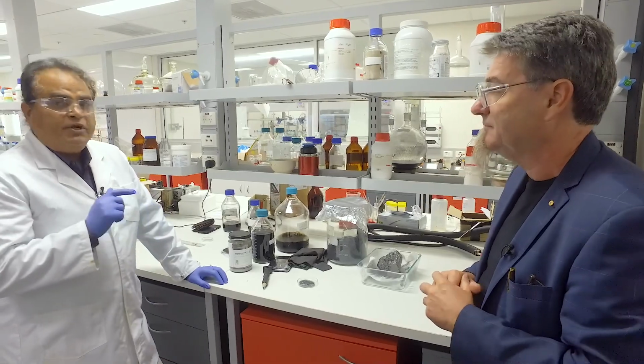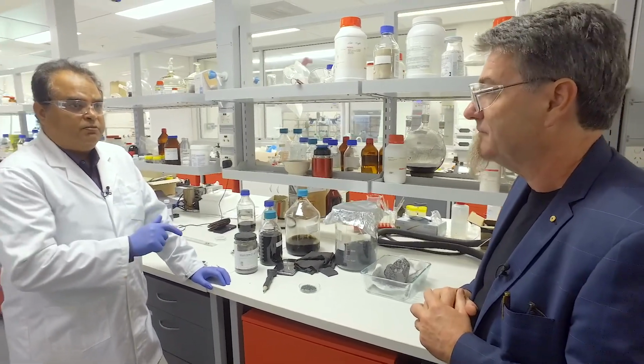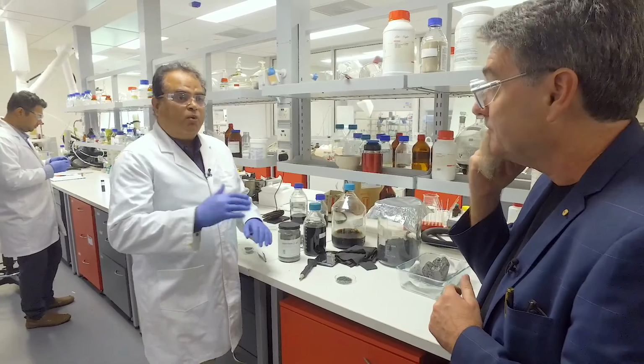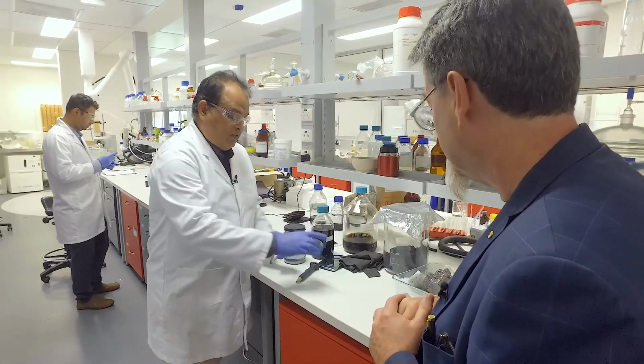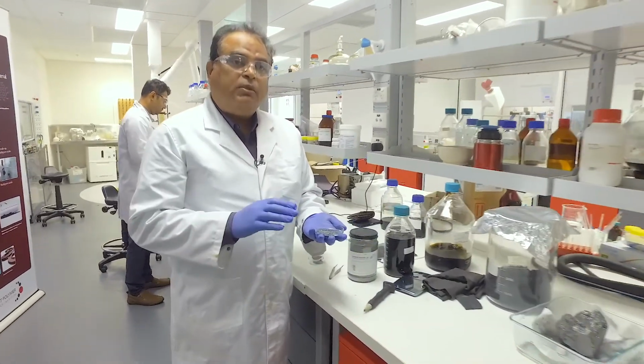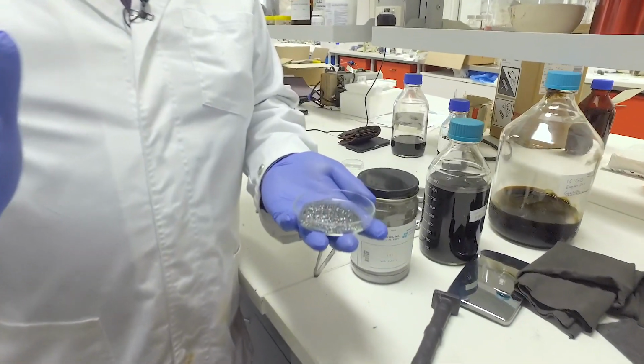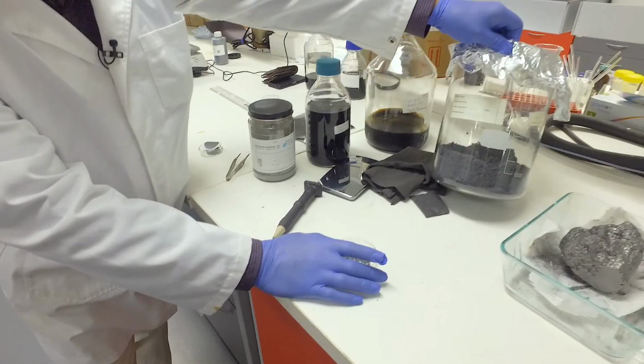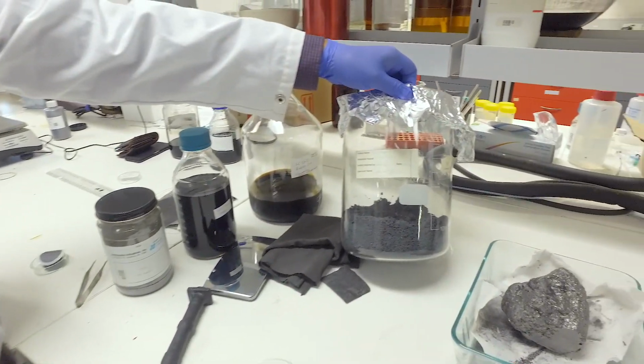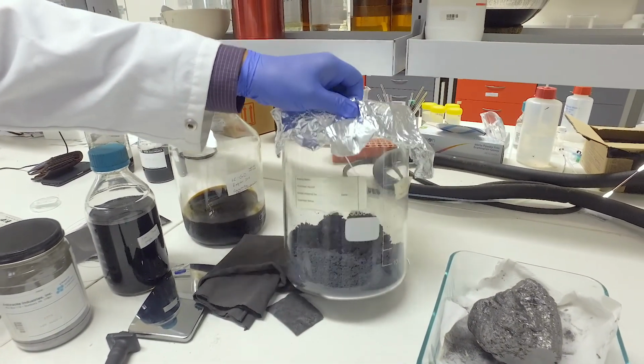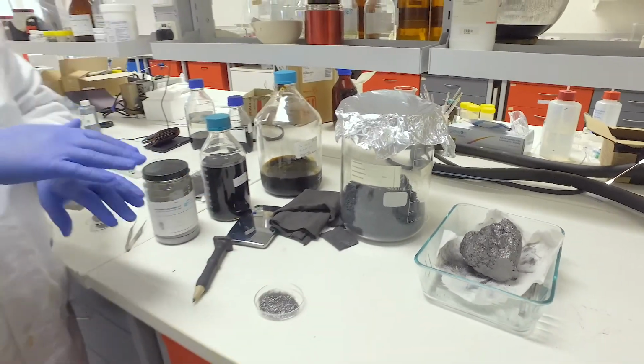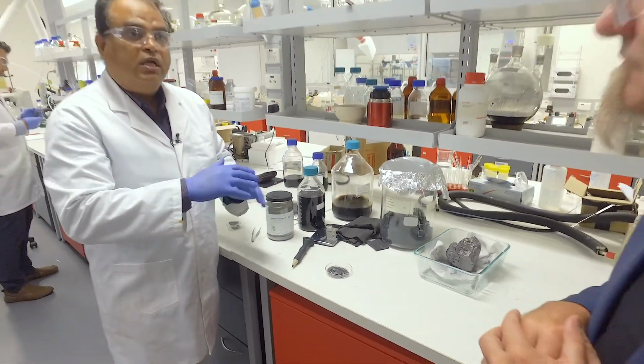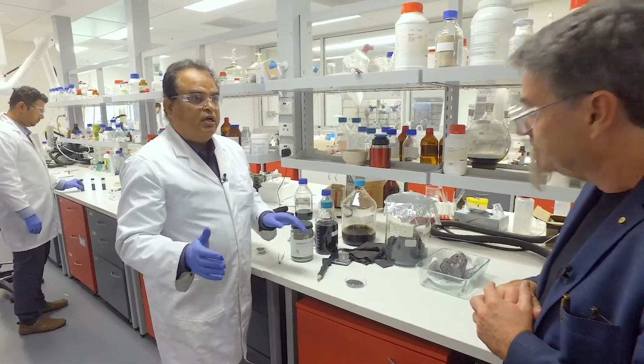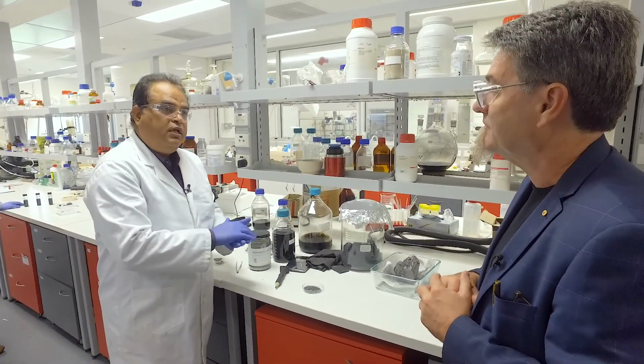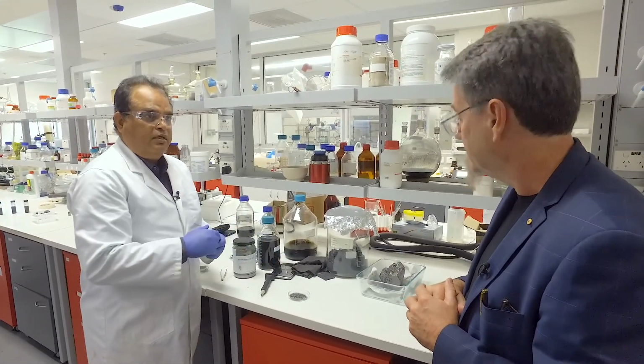Then we give a rapid thermal shock to this material so that it pops like popcorn. The volume expansion here, this is 2 grams of material, the volume expansion is between 700 to 900 times. So this much of material expands to this much of volume. Wow. So this is such a high expansion of this graphite. Once at this stage, now 7 to 9 sheets of graphene are stacked together. The surface area is very high. Now we can very easily chemically oxidize this material.